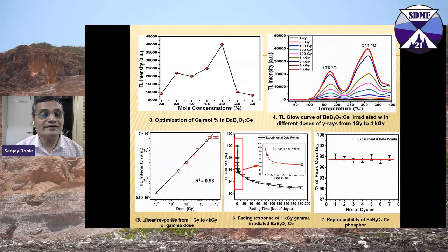Again, the concentration was varied. We observed that 2 mole percent is good enough. We have taken this one and increased the temperature, and then we could observe 2 glow curves. And this is the linear response curve that shows the gamma dose response from 1 gray to 4 kilogray.